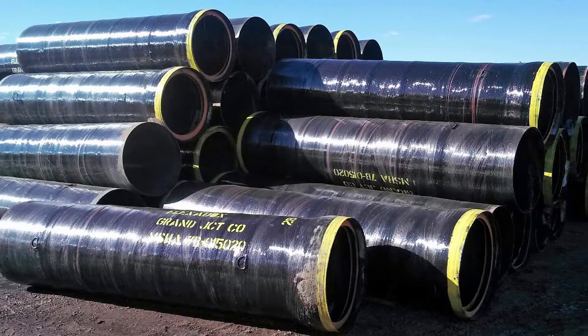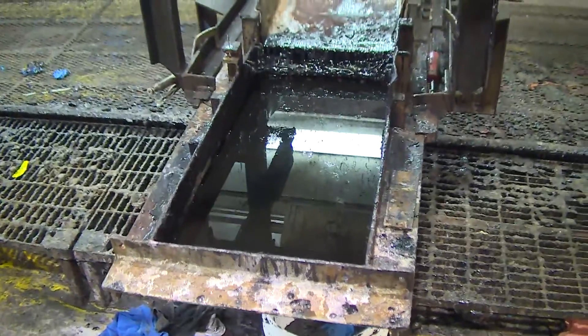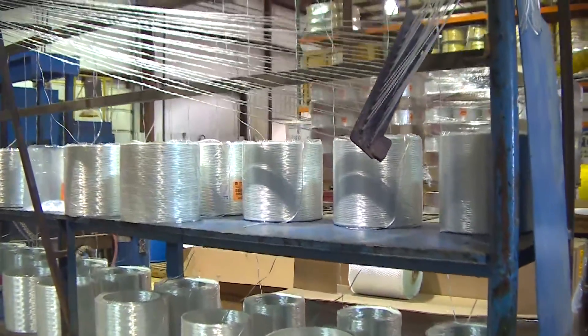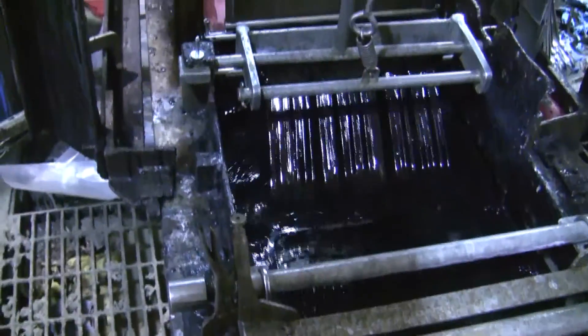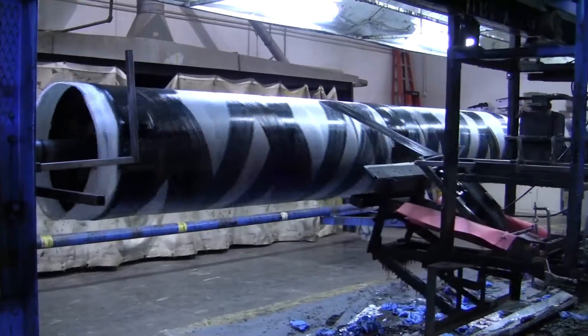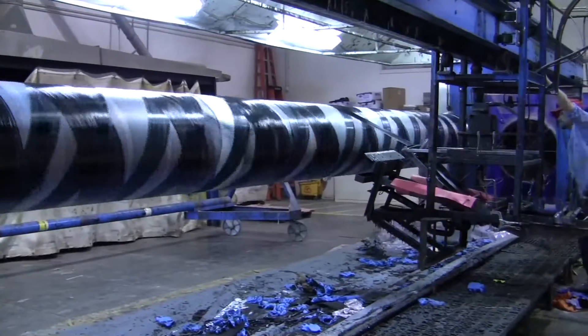This ducting can range from 1 foot in diameter to 7 feet in diameter. Filament winding is a process of fabricating composite materials in which continuous fibers are wound onto a rotating mandrel in a precise, predetermined pattern. The machine draws multiple strands of fiber through a bath of resin, which is then wound into a helical pattern up and down the mandrel. This pattern is determined by the rotational speed of the mandrel and the traversing speed of the trolley.